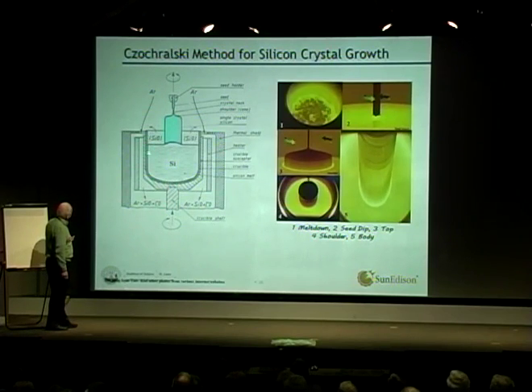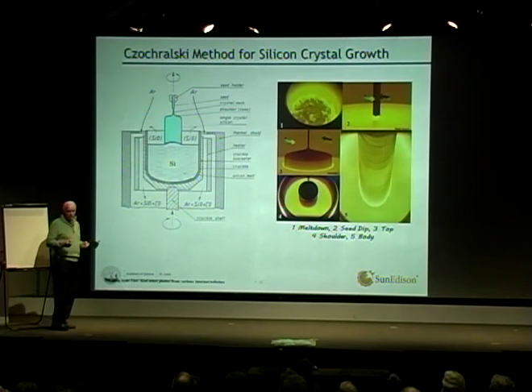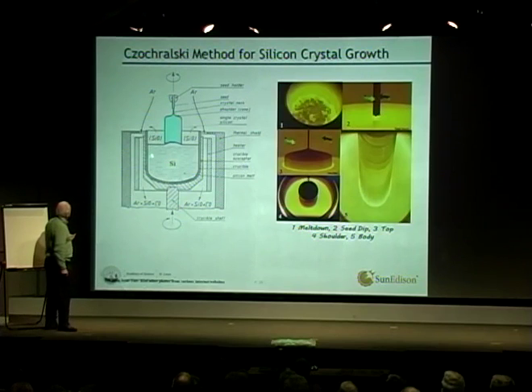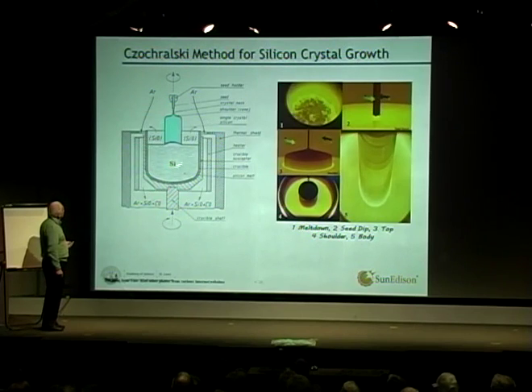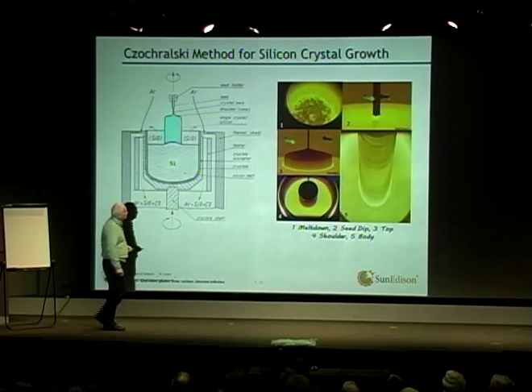And that's supported because, as you know, quartz is a type of glass. And as you know, when you heat glass up, it gets soft. So in order to keep this from getting soft, it's supported here in a piece of carbon. It's like an outer support on a pedestal so that this thing can actually rotate. And then we have a heater on the outside. And this represents the heater here. It goes all the way around. And so we put a lot of heat into this, heat this up, and it melts.